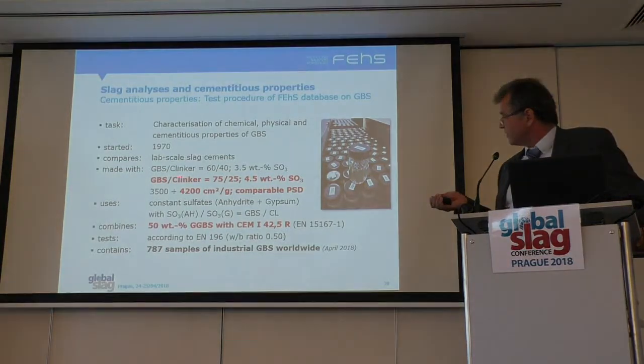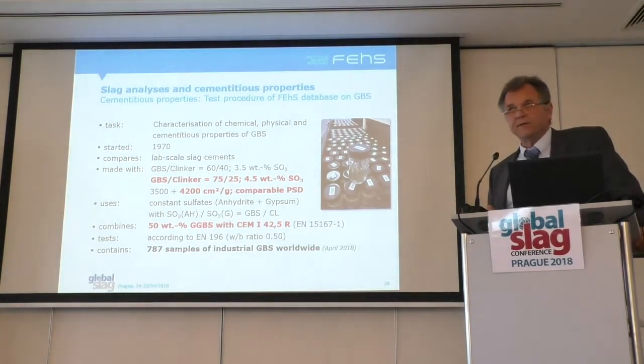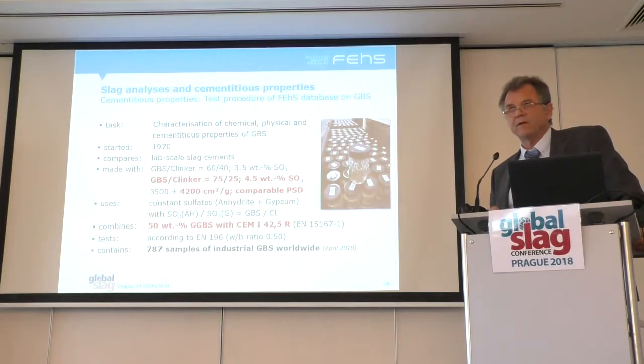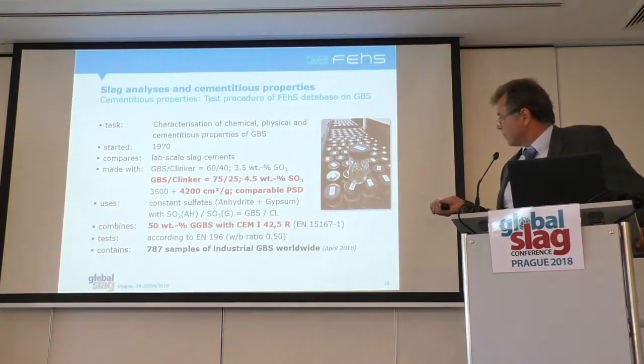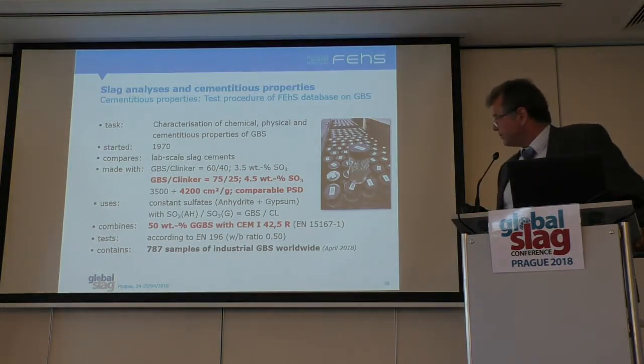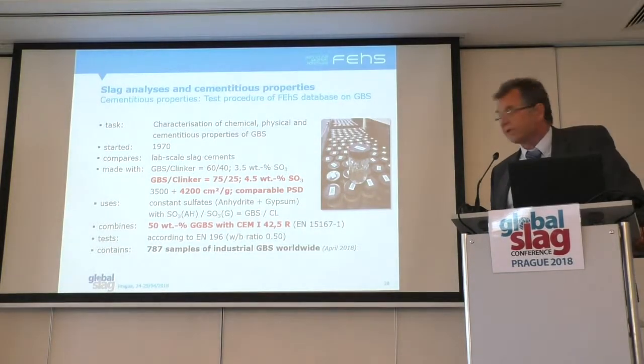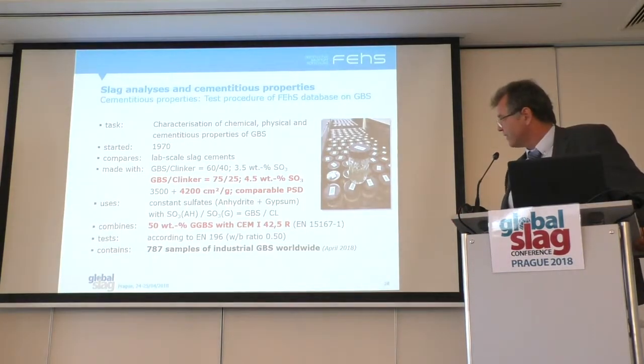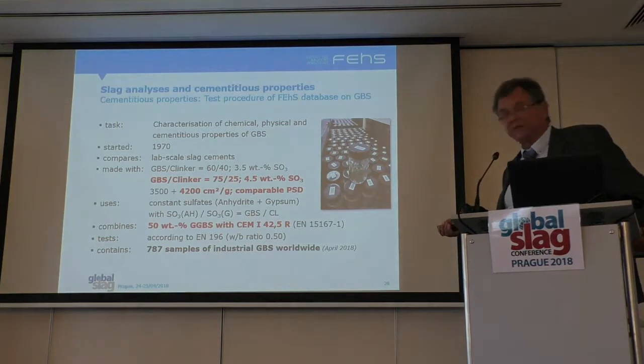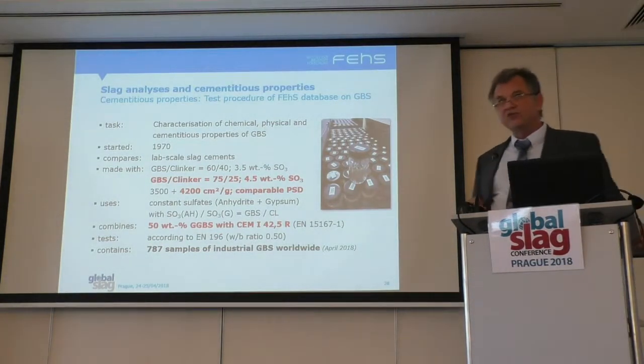Today we investigate mixtures 75% GBS, 25% clinker, and since the year 2000 we use really the same clinker which we grind if we need new material. The same sample, 2 tons of clinker which we stored in our institute. We install normally a comparable PSD, which is for a fresh slag about 4,200 Blaine. We use the same sulfates, the same sulfate concentration. We make also 50-50 mixtures according to the European GGBS standard.